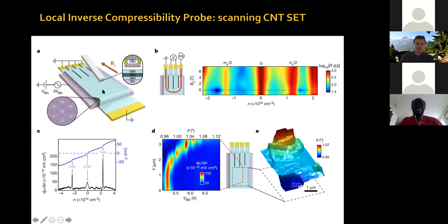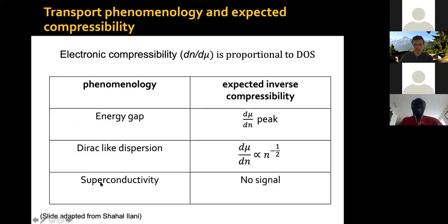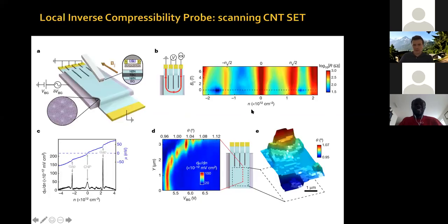Now, if you measure the inverse compressibility dμ/dn, this is a particular trace at a given spot, versus density. These are relatively high temperatures. I'll show you in a moment more detailed data. Look at the black curve. At 4 electrons and 4 holes per Moiré unit cell, you see a peak. Remember, I told you before in the phenomenology, if you have an energy gap, you should have a large peak. So you have this large peak because you have an energy gap there.